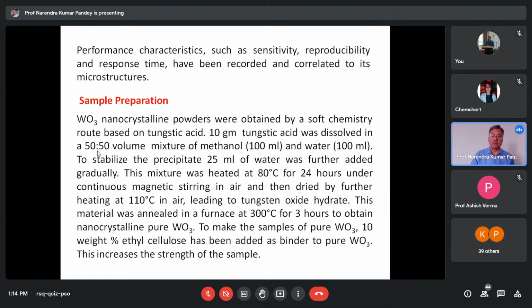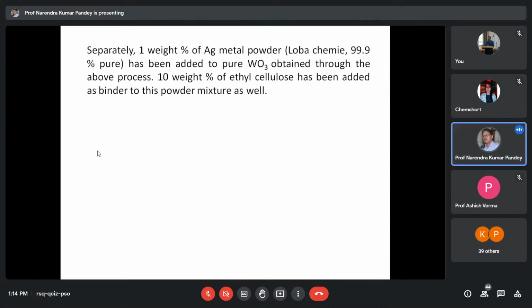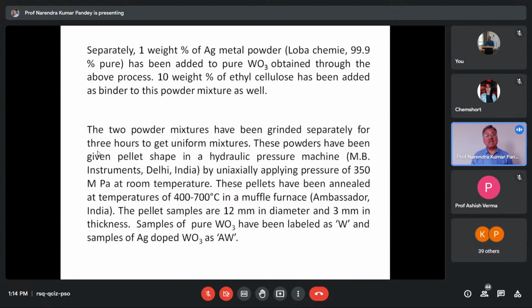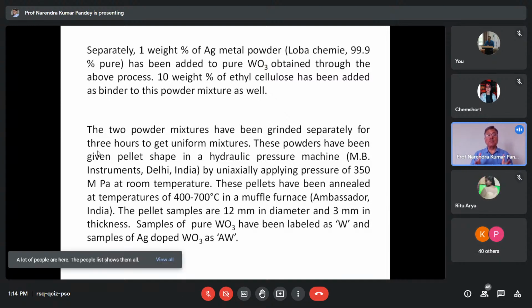To make the sample of pure WO3, 10 weight percent ethyl cellulose has been added as binder to pure WO3. Now this soft chemical route we have taken from the literature, and later we have added 10% ethyl cellulose from our side to make the sample stronger. So these methods are available in literature. Then we have added 1 weight percent of Ag metal powder to pure WO3 obtained through the above method. The two powder mixtures were ground separately for 3 hours. Mind it, if you grind for 1 hour, 2 hours, or 3 hours, you will have a completely different morphology of the sample. So everything has to be monitored.